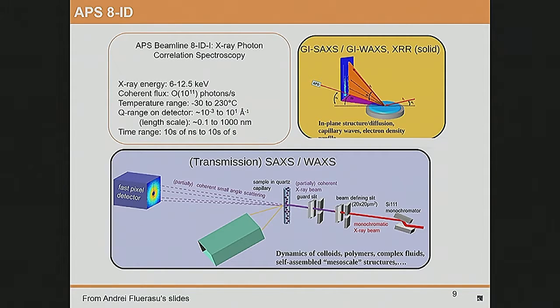So we had a lot of X-ray optics and an undulator that was important for that upstream. Then the X-rays, which were about energy 7.5 keV, scattered in transmission through our samples, which were a colloidal solution in capillaries. And the X-ray scattering, as Eric said, was on a detector downstream about 4 meters from the sample.